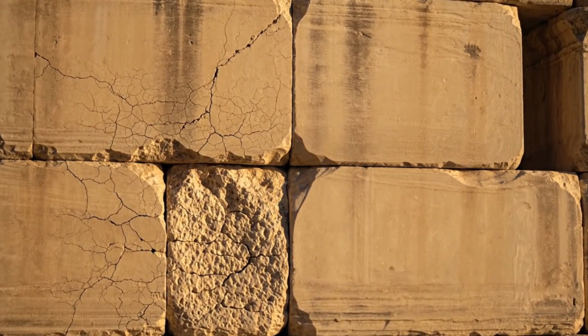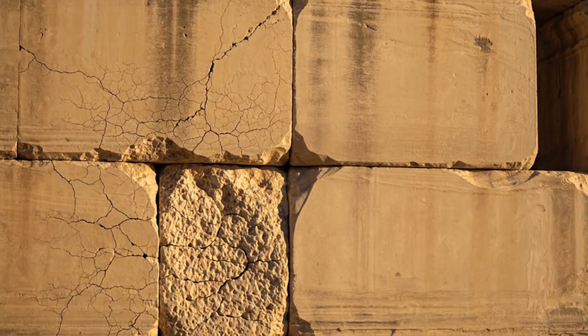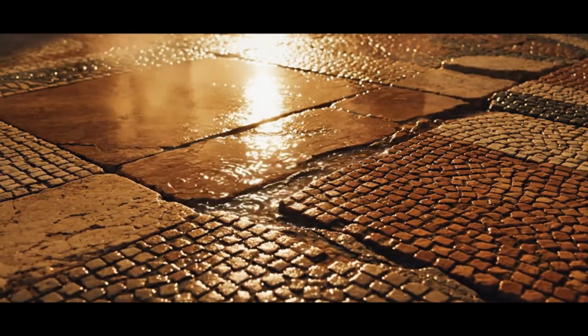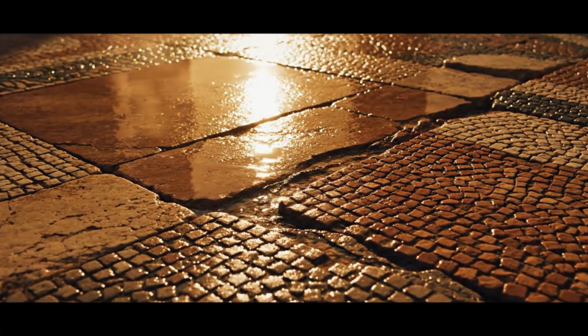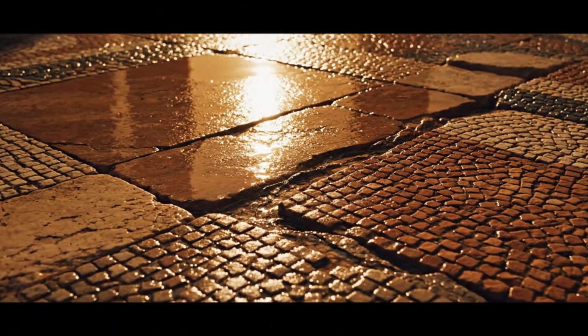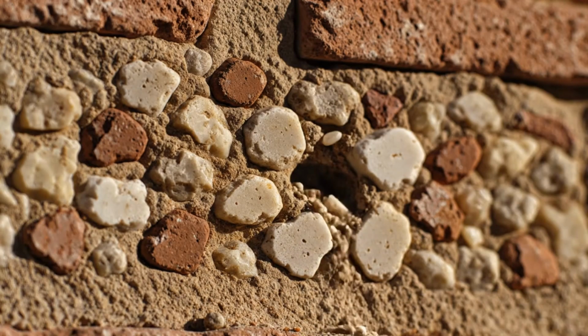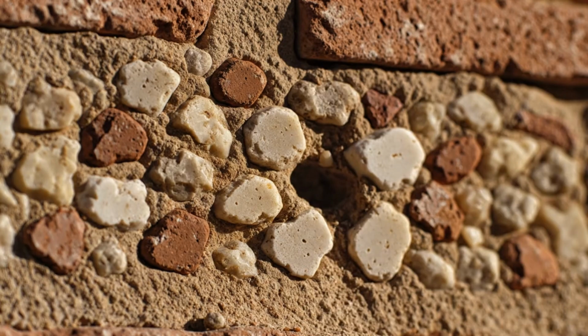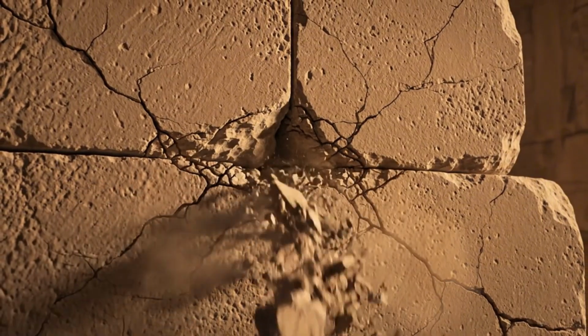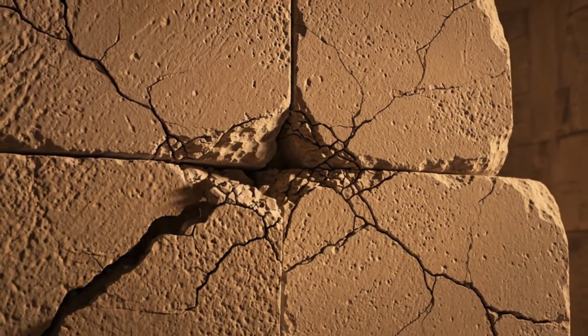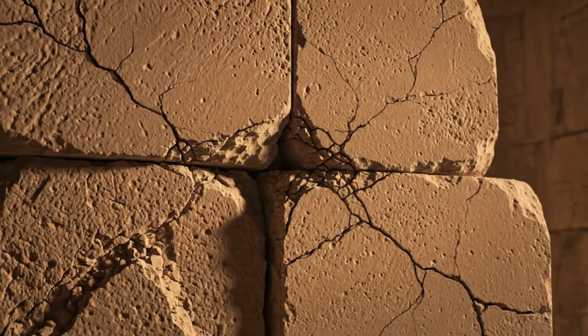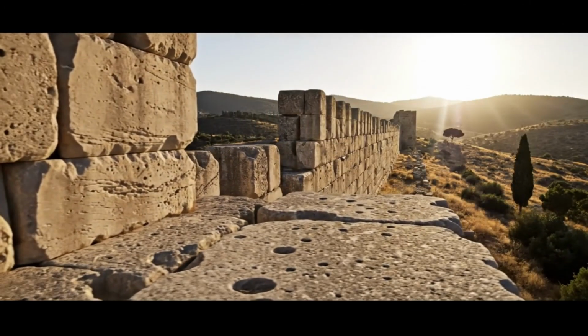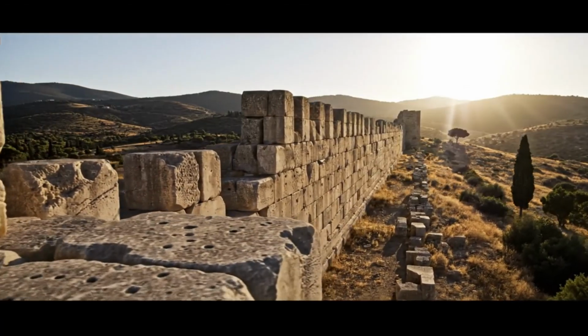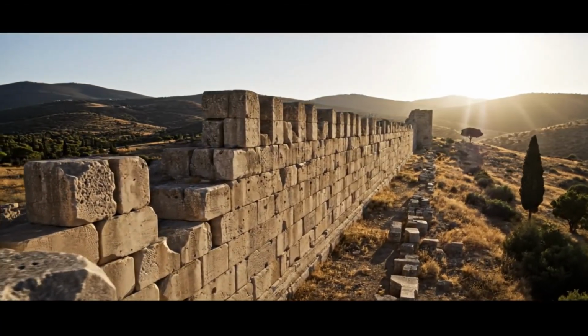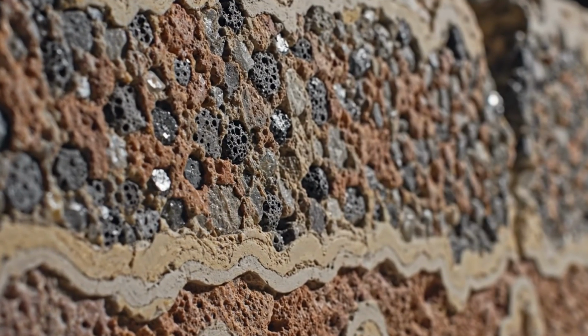Over time, this swelling generates internal stresses that lead to microcracking. These cracks frequently originate or widen along the interface between aggregate and paste, gradually weakening the entire system. Such deterioration illustrates a material fighting against its own chemistry. The very reactions that occur within modern concrete can undermine the bonds that hold it together. Once the interfacial zones are compromised, water and salts penetrate more easily, reinforcing a cycle of damage. Maintenance and repair become inevitable, and longevity depends on constant intervention.